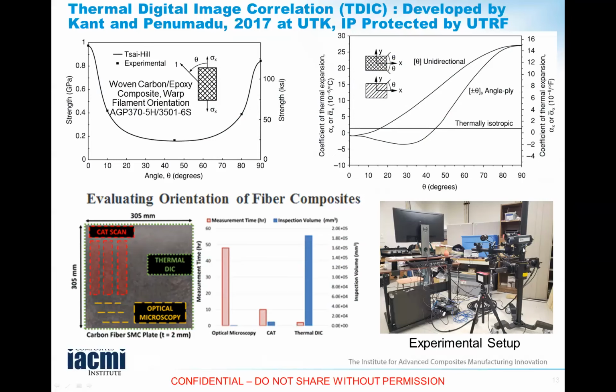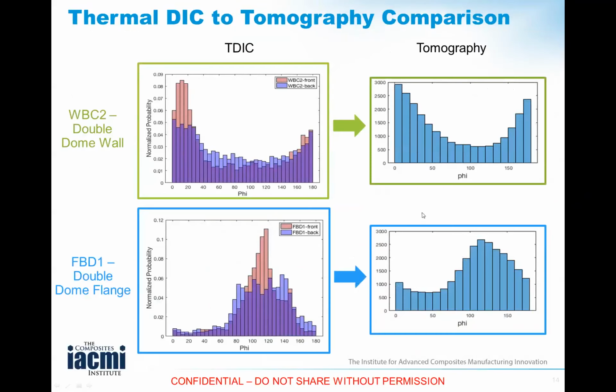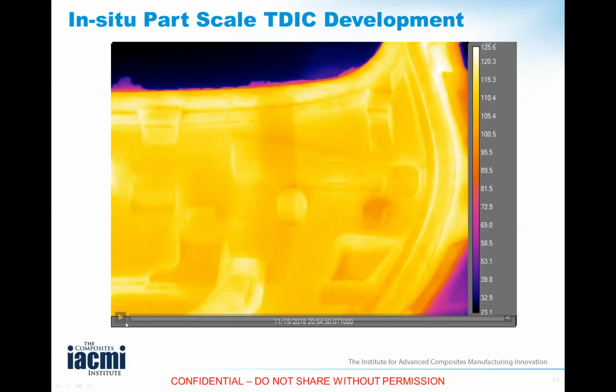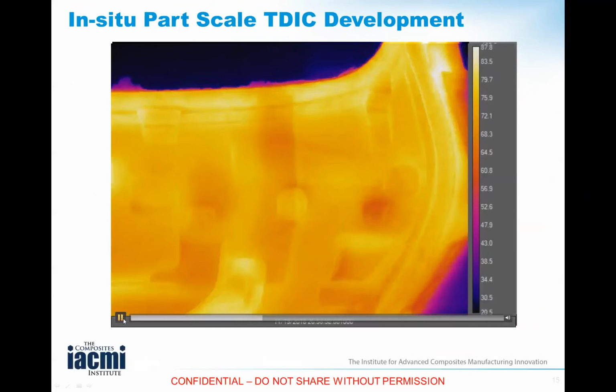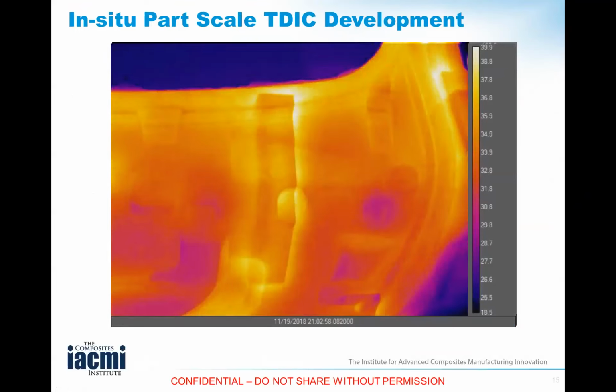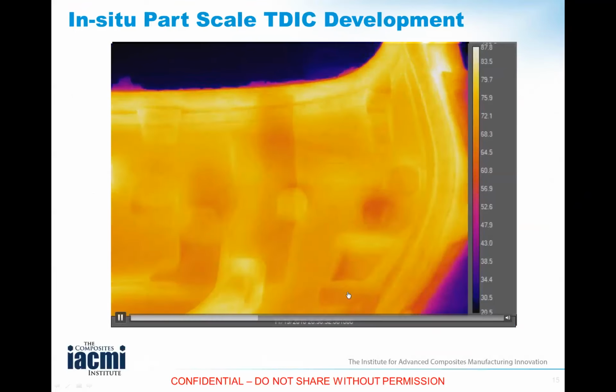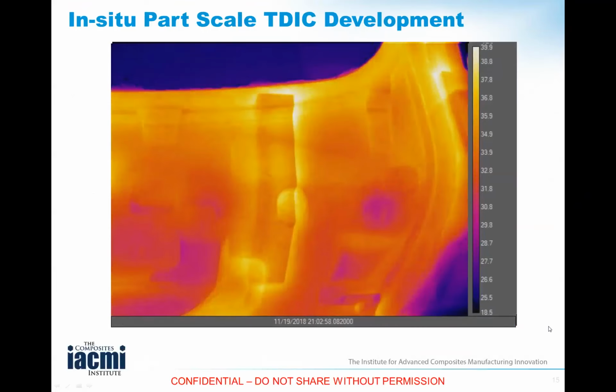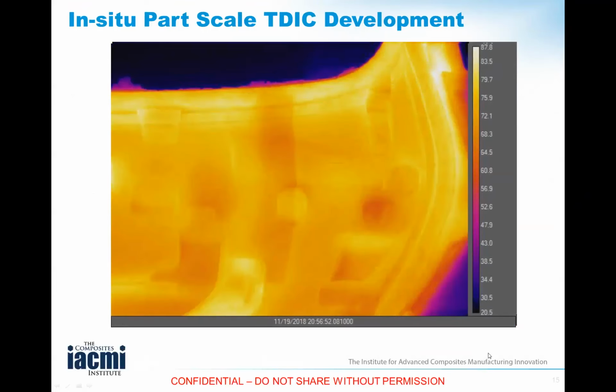So our technique essentially has the components. We have two optical cameras and one thermal camera, and from this information and the anisotropy of the carbon fiber thermal expansions, we derive the orientation. This is a high-level comparison to show that our TDIC works quite well compared to tomography. And this is an example of a molded component that shows you how temperatures are varying as the part is cooling. So we take this into account and then couple that with the measurement of spatially resolved strain.